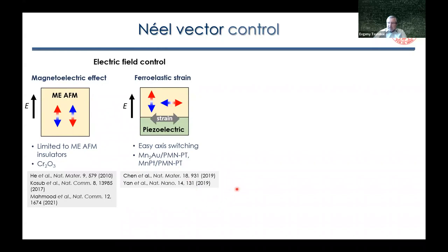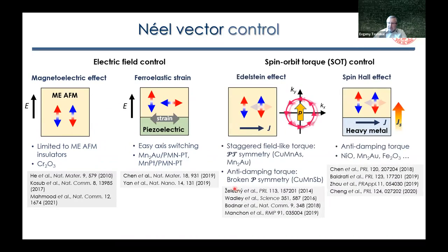So at the same time, there has been some very active work in using spin-orbit torques. So we know that spin-orbit torques can be efficiently used to switch magnetization in ferromagnets. So it appears that a similar related idea can be used for antiferromagnets. I give you a few examples here. For example, it was shown that for certain types of antiferromagnets, like, for example, copper manganese arsenide, which have PT symmetry, where P stands for space inversion and T stands for time reversal symmetry, one can produce staggered field-like torque, which can switch the antiferromagnetic order parameter.